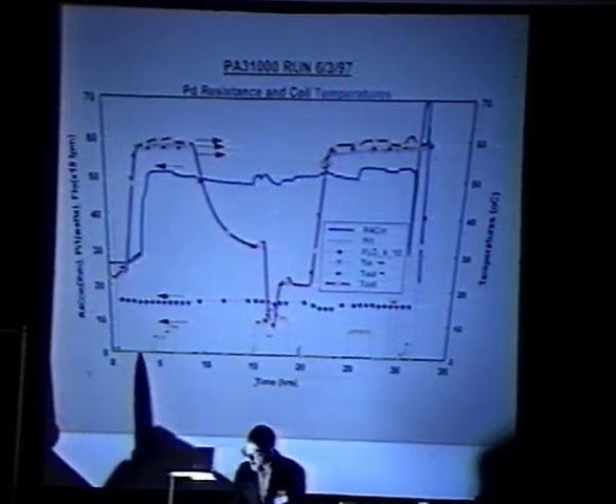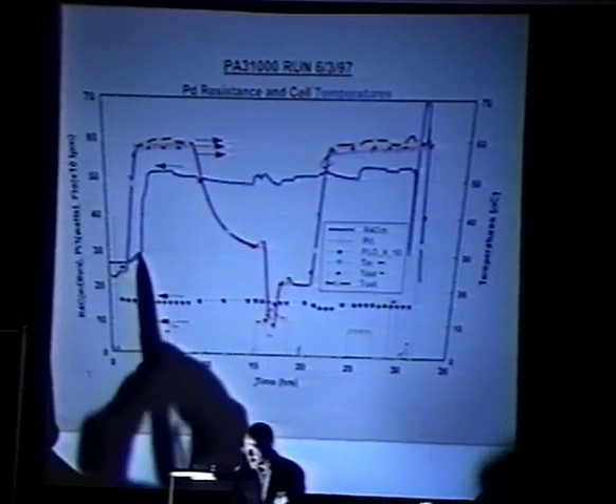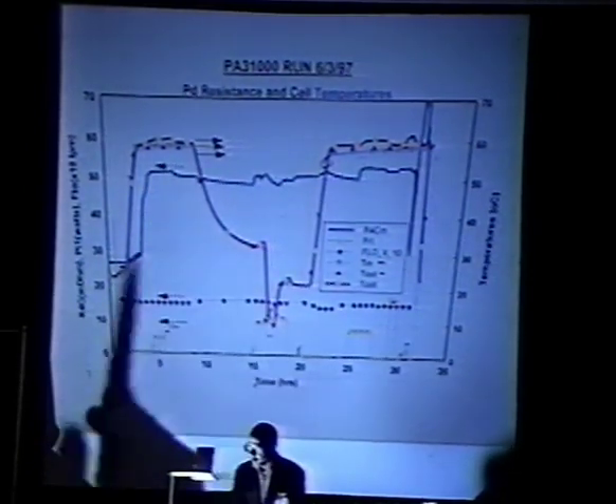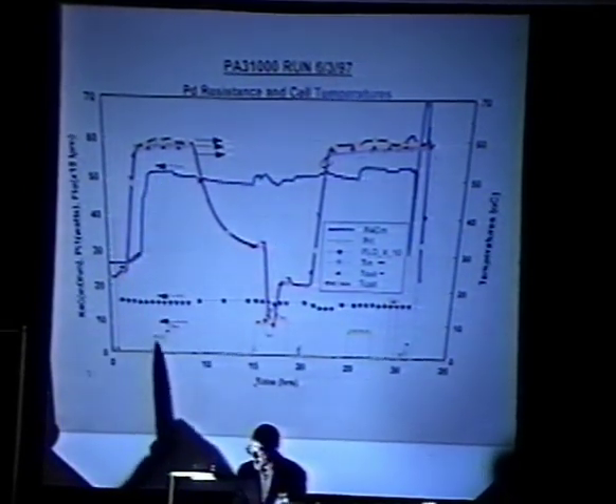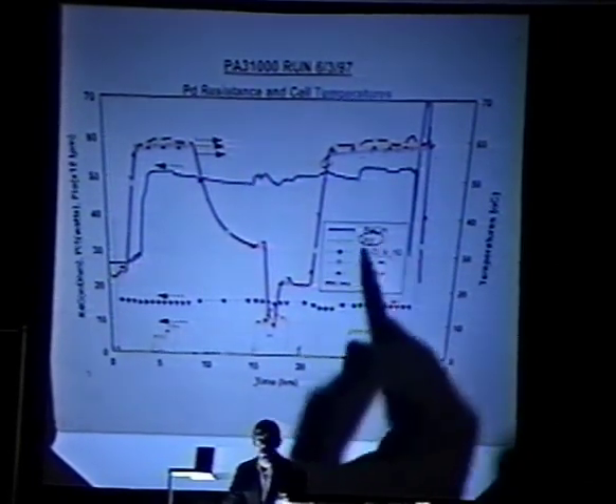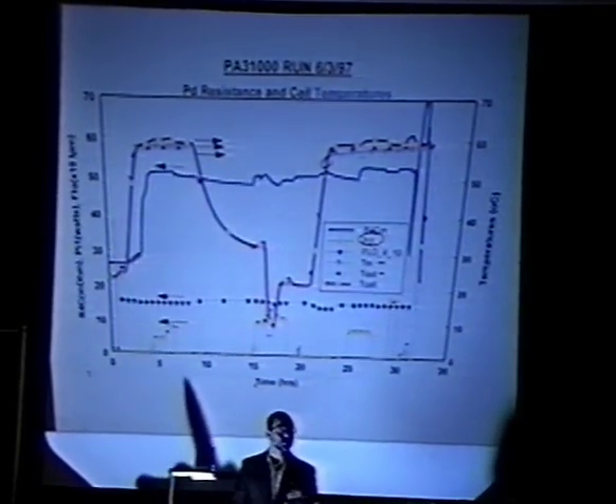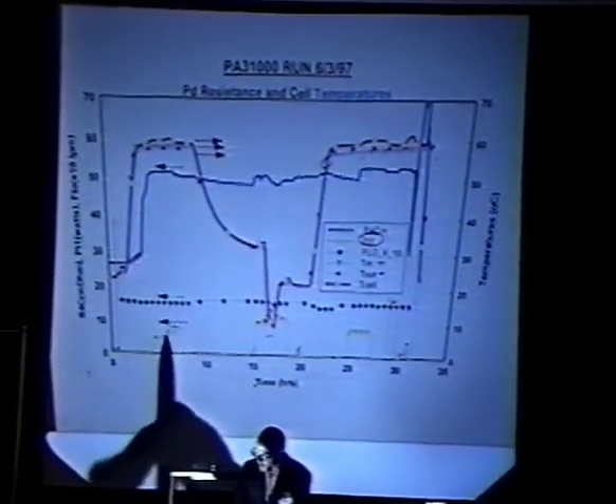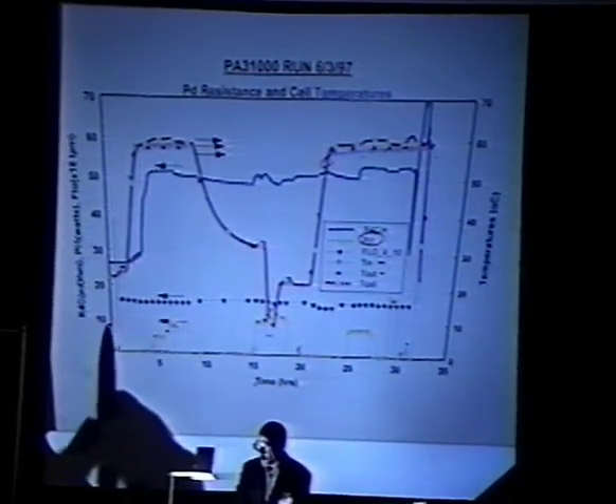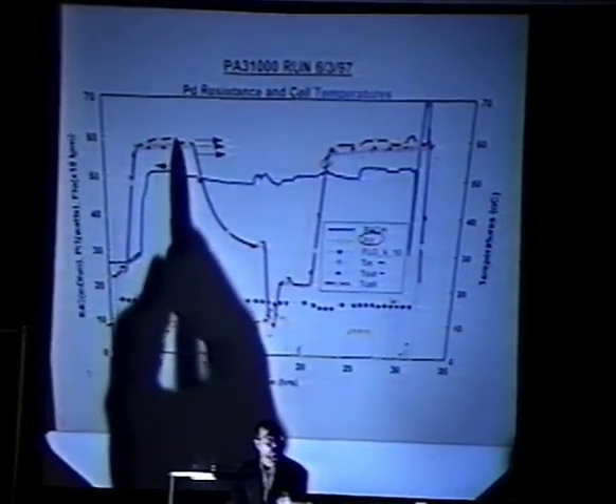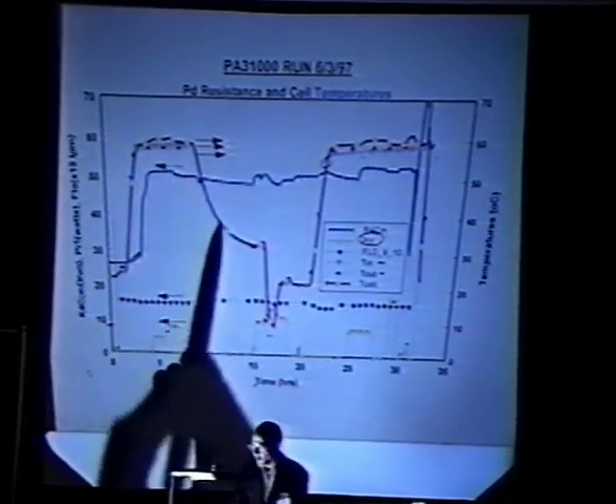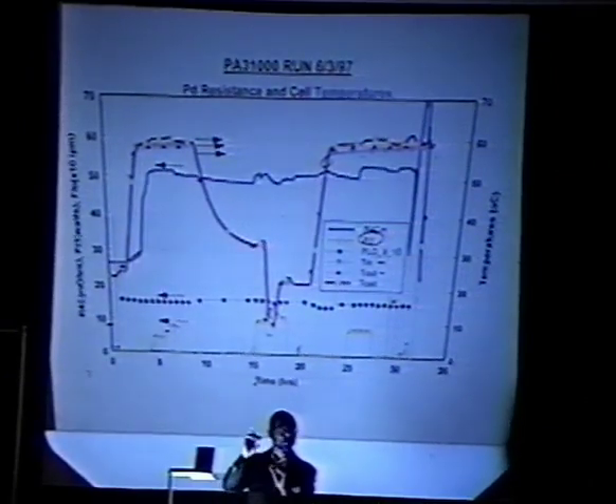And at this point in the run right here, what you see, there's a very small current turned on that actually starts this thing to charge. And you'll see the resistance come up and peak. And all during this time, notice the current now is coming up. This is current, I've actually listed it as what's called the inlet power, the input power. It's electrical current times the voltage across the cell that's going in. And you can see these numbers here on the order at maximum about 8 watts. And when you get the 8 watts in, you can see the temperature of the cell come on up above the calorimeter. So these yellow plots and red is the average of the two cell temperatures.